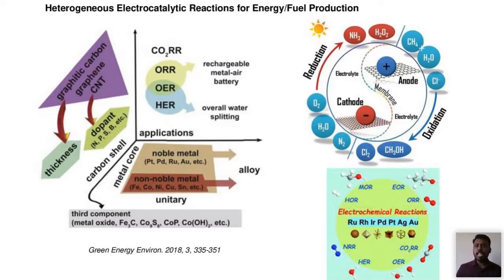You can also design different shapes or structures, like carbon shell and metal core. Metals always tend to be prone to corrosion in acidic or alkaline environments. You can protect the metal active sites by forming a carbon shell. In that way, you can increase the stability. You can also introduce some third component like iron carbide, cobalt sulfide, phosphide, or hydroxide. These are very good for evolution reactions like hydrogen evolution and oxygen evolution reaction.